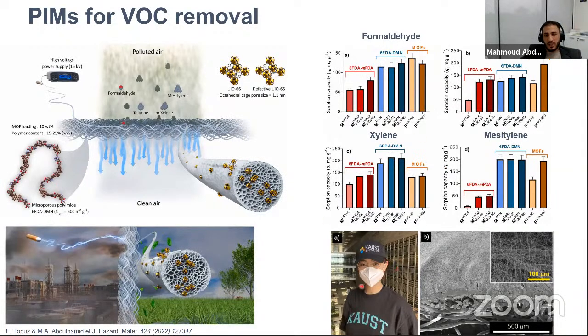For a direct application, we wanted to see if we can electrospin these nanofibers onto a face mask, because we can apply this in regions where the air is highly polluted, using a face mask coated with this type of polymer. And we were able to, as you can see in the SEM, integrate and add this polymer on top of the face mask for VOC removal.